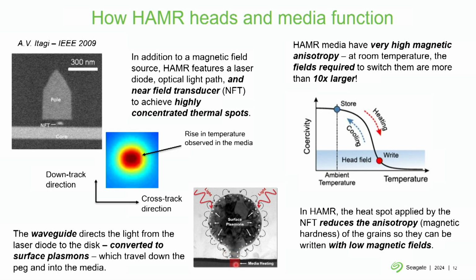So there is a thermal spot created in the media that's as large as this peg. And we can make this peg pretty small. So now the bit size is determined by how small we can make this peg. And the thermal spot that's generated in the media can be quite small and at very high temperatures, so above almost 400 degrees C. And the thermal gradients, which are really important to us, so how fast the temperature falls off, is very significant for these thermal spots produced by the NFTs.